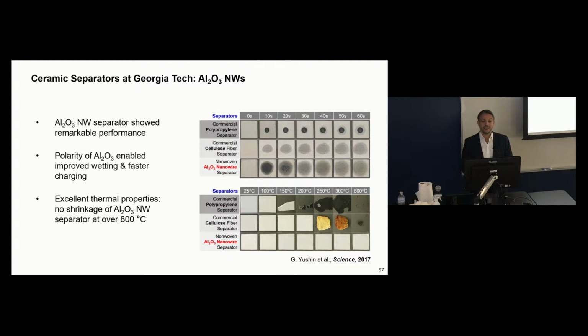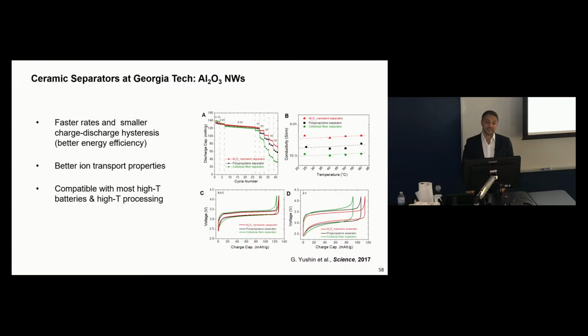And so once you have these oxide nanofibers, you can make ceramic paper out of them. You simply replace cellulose fibers with the ceramic fibers, and you produce ceramic paper that has very good properties. It has a very good wetting behavior. It has a very high dipole on the surface, so electrolyte wets really well, and so you can have very fast charging in batteries. It also has remarkable thermal properties. You can heat it to 800 C, and it is not going to shrink because it's ceramic. So again, very good behavior for battery applications. And so if you cycle batteries, you will see smaller hysteresis, better behavior, and high rate performance of the separators.